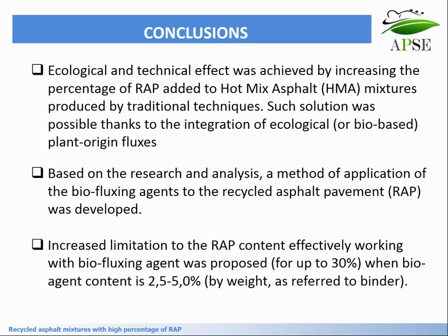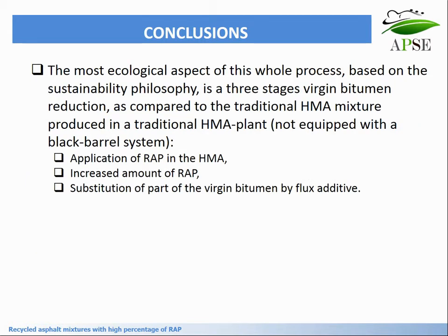In final conclusion, an ecological and technical effect was achieved by increasing the percentage of RAP added to the mixture using traditional techniques. Such a solution was made possible thanks to the integration of ecological plant-origin fluxes. Based on the research and analysis, a method of application of the bio-fluxing agents to recycled asphalt pavement was developed. The RAP content limit effectively working with bio-flux was proposed at up to 30%, when bio-agent content is 2.5% to 5%. The most ecological aspect, based on sustainability philosophy, is a three-stage virgin bitumen reduction: application of RAP in HMA, increased amount of RAP, and substitution of part of the virgin bitumen by flux additive. Thank you very much for your attention.